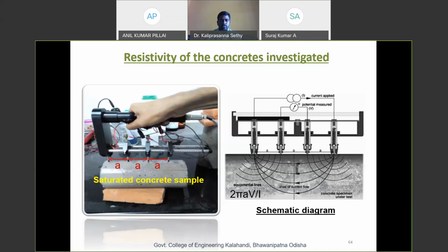So here we have used the 4-probe technique. You can see from the schematic diagram, here are the 4 probes. The current passes through the outer probes, where the voltage drop is calculated using the inner probes, and using this, the resistivity is rho equals 2 pi a into V by I. So we calculated the resistivity for all the normal and self-compacting concretes.